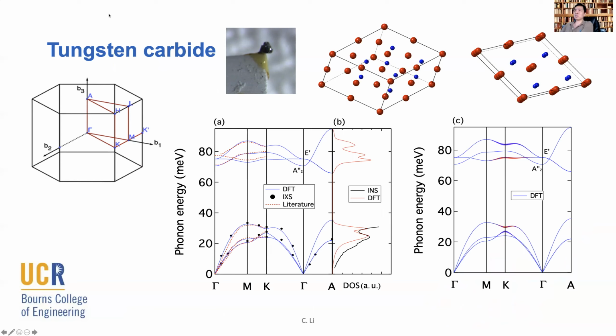Tungsten carbide is one of those we can easily get access to as single crystals. Here I'm showing the small single crystal we measured with inelastic X-ray scattering. And this is basically what the lattice looks like. If you spend some time looking at it, you can tell there is a broken inversion symmetry somewhere, and you cannot reproduce the periodicity of the lattice by doing a spatial inversion operation. And here I'm showing our calculation versus our measurement, also overplotted with some literature calculation.